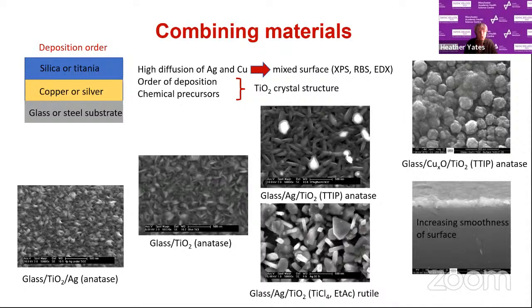So how do you combine the materials? Well, what you find, if you put one on and then the other, you don't get thin layers of either. They tend to mix, mainly because both silver and copper diffuse highly at temperature, so you end up with a mixed surface. This mixing of surface also changes what order you have and the structure of titanium dioxide, because it's got two crystal forms. So looking at the structure on the glass titania, it's got anatase. If you put silver on top, it doesn't really change the surface. The picture on the left, it looks very similar.